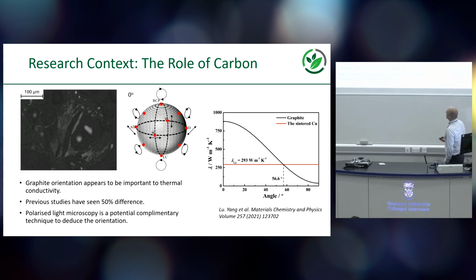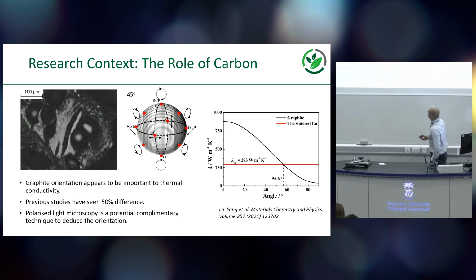And we did some interesting work where we looked at how we might be able to determine that relatively rapidly using simple characterization methods. So this is actually just an optical micrograph. It doesn't look like one because we've used only polarized light, so only light that's incident in one direction, and it happens to interact with the graphite in a way that tells you what the crystal orientation is. So if you look at this through a whole series of different rotations of that single plane of light, you can see that you get different colors.